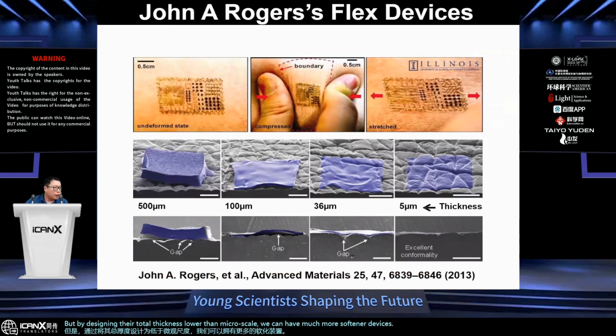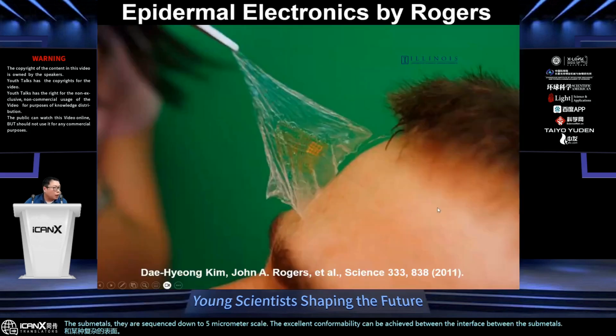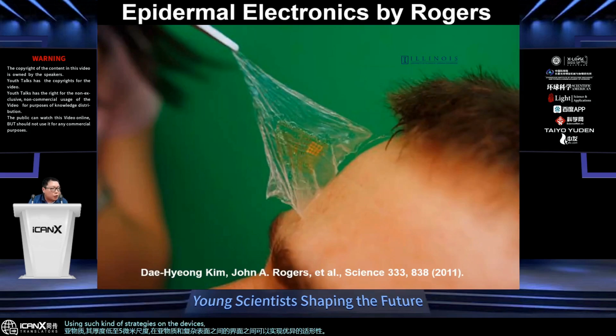Here is one good example published by Rogers Group in 2013. They showed that a metal whose thickness is 500 micrometers on top of a very complex surface shows an air gap between the metal and the complex surface. But with metals whose thickness is down to the 5 micrometer scale, excellent conformability can be achieved at the interface between the metals and the complex surfaces. Using such a strategy, they could demonstrate multifunctional sensors on forehead surfaces, and finally get biological information, such as temperature, sweat information, and electrocardiogram data.